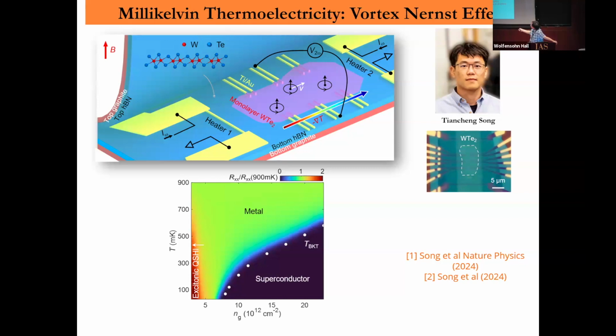It's basically something like this, and of course we have electrodes here so we can check transport. This is the typical transport we observe as a function of density—we dope electrons into the material—and temperature, so you tune the external state from insulating to superconducting.